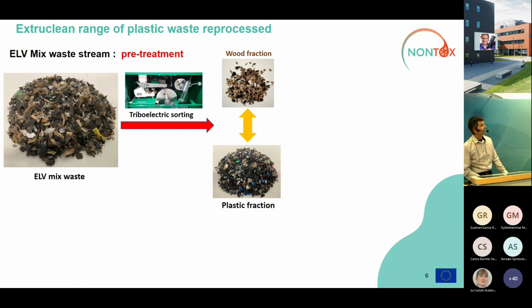So in this case, as a pretreatment, we propose a triboelectric sorting technology that relies on the different electrostatic charge capacity of the materials in order to get rid of the wood fraction that is heavily present in this type of mixed waste, and to separate the mixed plastic fraction.